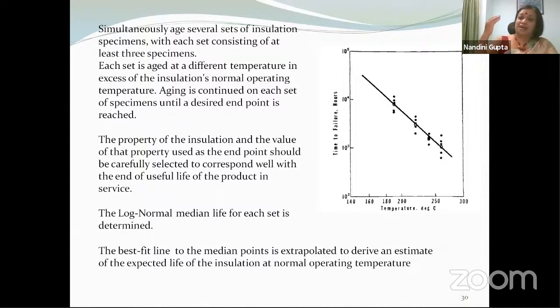You cannot set a high parameter when you know that in service you're not going to be able to replace when the brittleness reaches that point or the conductivity reaches that point. So that is where your engineering judgment comes into the picture. Once you have the data, you will plot the log normal median life for each set. The best fit line to the median points is then found. You can use some statistical technique to fit a best fit line to the data.